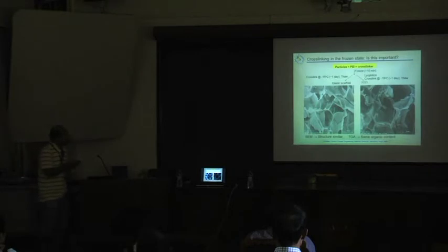What we then did is, after we froze this material, after about 10 minutes, we pulled this sample out and then we sublimed off the ice. So we took it to minus 80 Celsius where there's no reaction that happens, and then you pull a vacuum on it so that the ice comes off, but the structure of that porous structure is retained, and then you put it back into the freezer, and then you allow it to cross-link.